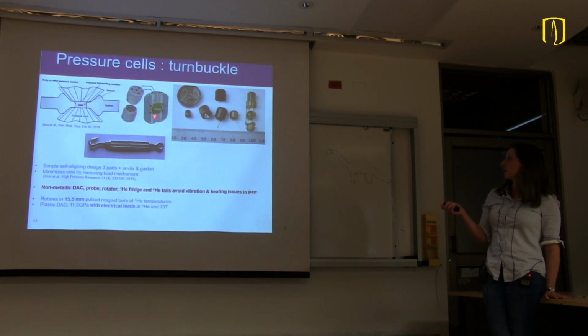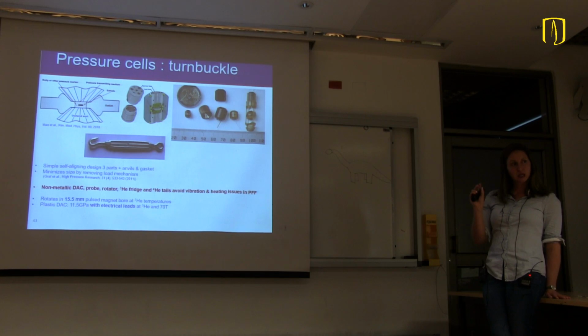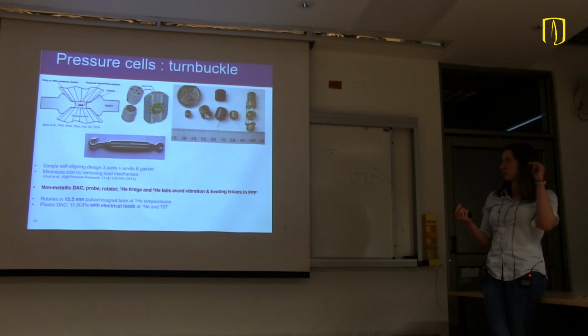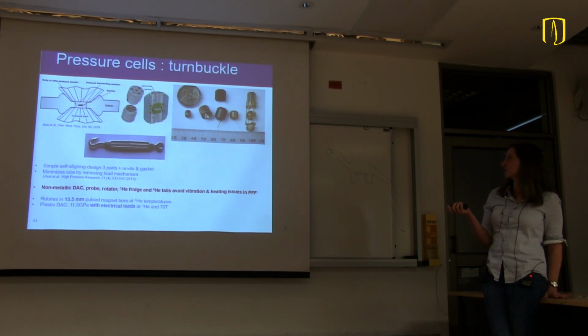And this is the schematic of one of our pressure cells. You put the diamond anvils in those 2 end caps. There is a thread here, so one is left-handed, one is right-handed. You put those 2 caps in a body, the greenish part around, that has matching threading. If you rotate the body around, it brings the 2 anvils closer together, and that's how you generate and retain high pressure. So it's a very simple mechanism.